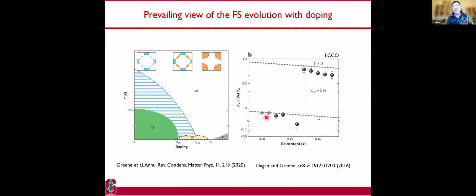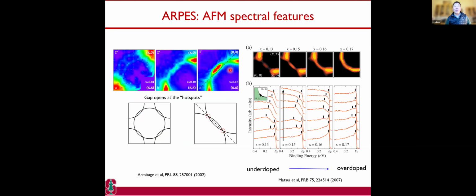This is also seen by transport, where you can see a sudden change of transport properties of the carriers, consistent with the jump from a smaller pocket to a large Fermi surface. And this sort of behavior in angle-resolved photoemission is already there very early on in Peter Armitage's thesis, and also Matsui showed additional development in this. But overall, it's a very clear picture. The antinodal pocket dominates, and depending on your doping, you can see the emergence of this piece of Fermi surface, and connecting these two is the famous antiferromagnetic hotspot. That is the spot where the unreconstructed Fermi surface crosses the antiferromagnetic zone boundary. So you can see this from the underdoped to the overdoped system.